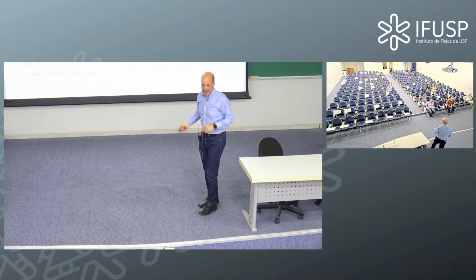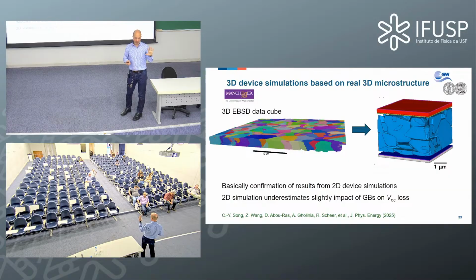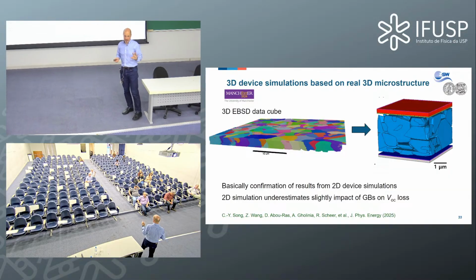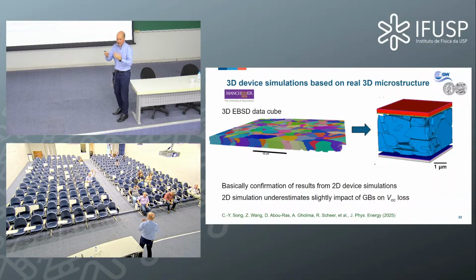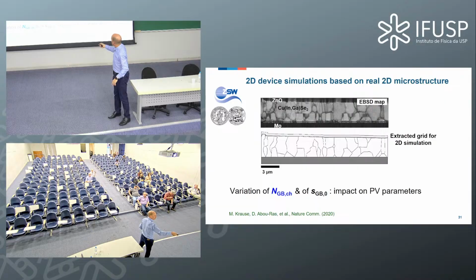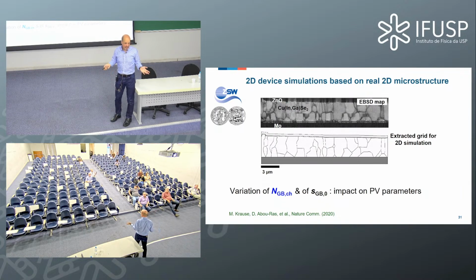And the 3D case here, I forgot to tell you, was actually applied to 5 different cells, not just one cell. So it can be seen quite easily when comparing 2D and 3D for all 5 cases. 2D is okay, and it's already better than having an arbitrary grid. There are some very funny papers showing only grain boundaries going from top to bottom, or grain boundaries like this, or even only like this. But it's simply this limitation.